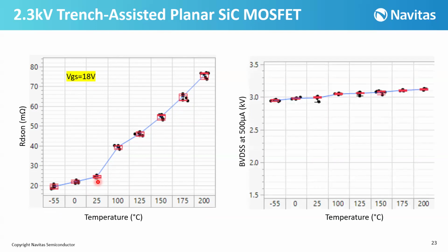Here's the breakdown voltage at 500 microamps. At room temperature, the breakdown voltage is around 3 kilovolts for 2.3 kilovolt class MOSFETs, and we have a stable breakdown voltage. And as you know, the breakdown voltage increases a little bit in silicon carbide devices from low temperature to high temperature, and we can see this trend here from -55 to 200 degrees C. So at 200 degrees C, for example, the breakdown voltage is around 3.1 kilovolts at 500 microamps.